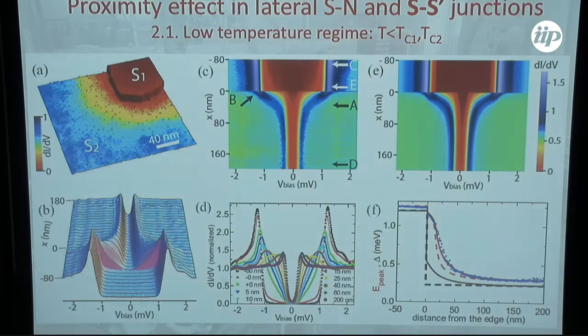I just want to tell you one thing, because it's very important for recent discussion. When you do a proximity effect, abusively, we always say that we induce superconductivity in the normal metal. In these two papers, we show that if the normal metal is a superconducting material with low critical temperature, you can indeed induce a superconducting order in it by proximity with a stronger superconductor. So you will get real Cooper pairs.